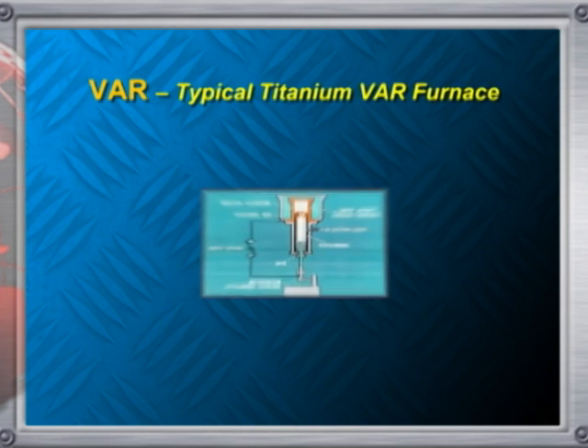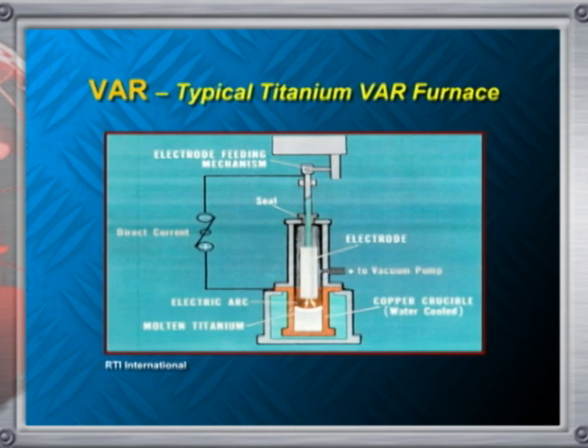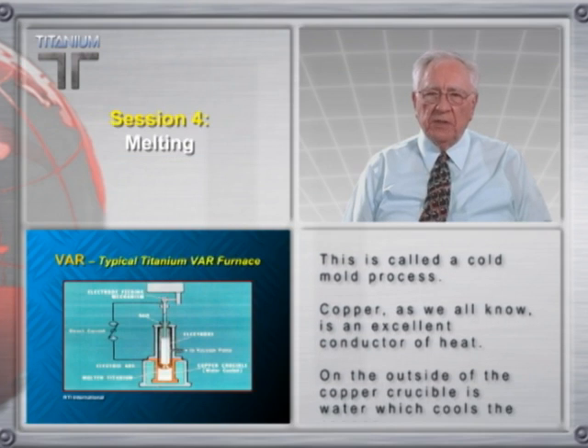This depicts the details of the actual melting furnace. The metal is melted by a DC electric arc maintained between the electrode and the crucible. The electrode is gradually consumed and an ingot is formed in the bottom of the crucible. Note the crucible is copper. Recall carbon and oxide crucibles were initially tried, but they reacted with the titanium. This is called a cold mold process.